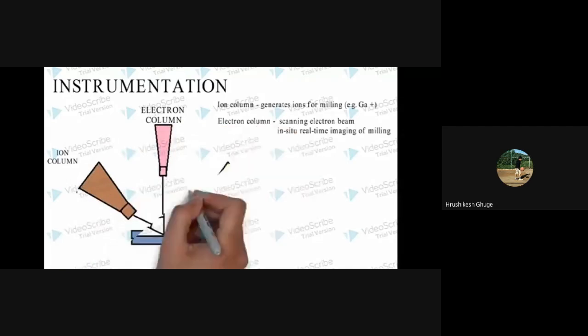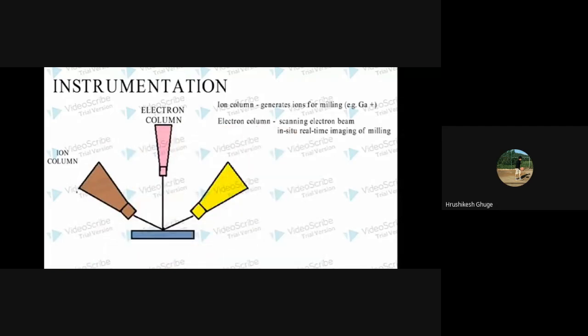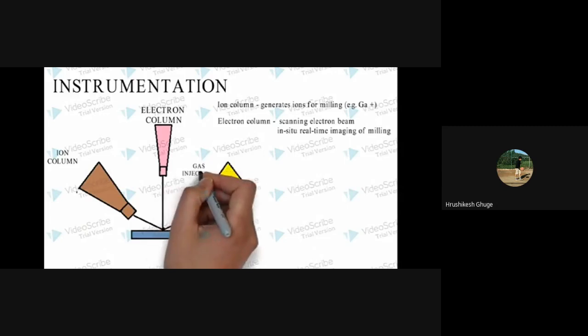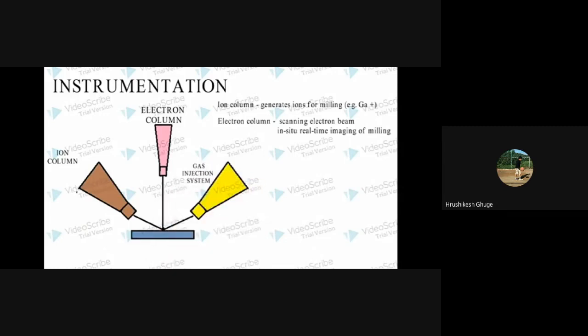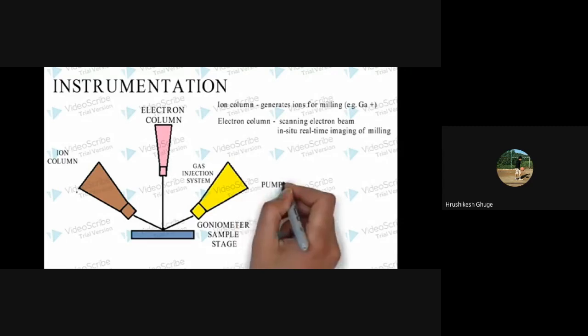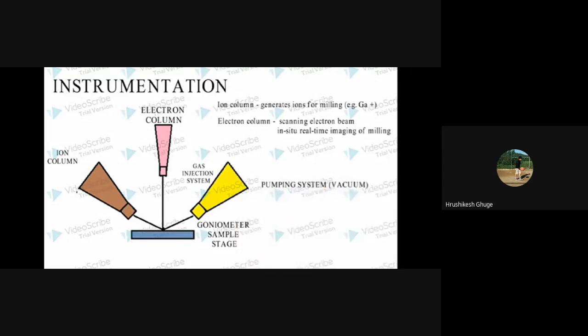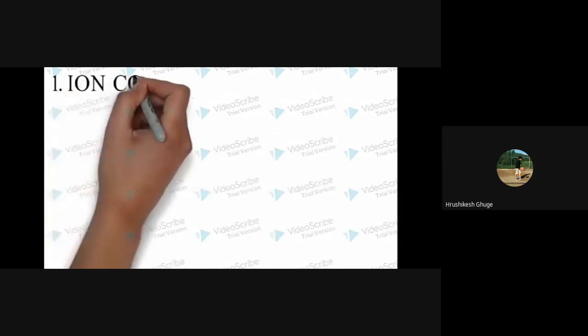In case of gas-assisted FIB machining, there is another nozzle in the setup which is from the GIS, that is the gas injection system. So the instrumentation also includes a goniometer sample stage, that is the stage on which the substrate or workpiece is held, and a pumping system for creating vacuum conditions suitable for both the electron beam and ion beam. So there are a total of five aspects: ion column, electron column, gas injection system, goniometer sample stage, and pumping system.